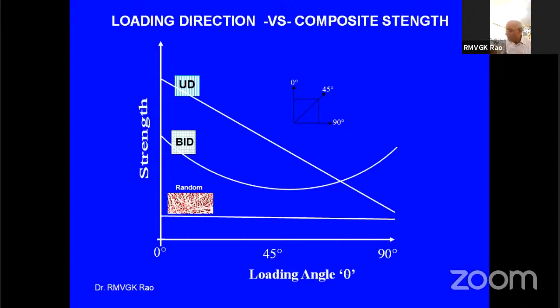So that's why the bidirectional composite, the BID, is very good in that sense. It has balanced properties on the x-axis direction, y direction, as you have seen in the previous slide. So at the extreme, it's 0 degrees. When you load it at 0 degrees along the warp direction fibers, you get some strength. And when you load it along the weft direction, 90 degrees, you get the same strength. You see the U curve. It is here 0 and 90 is practically the same strength. And in between at 45, it falls down. So the strength of the composite, in addition to the direction in which it is laid, also depends on the direction in which you test it.